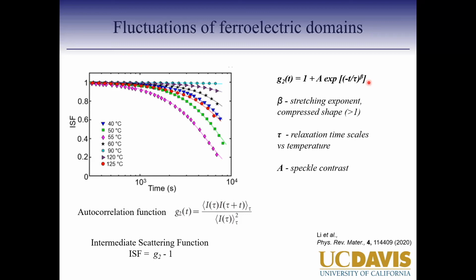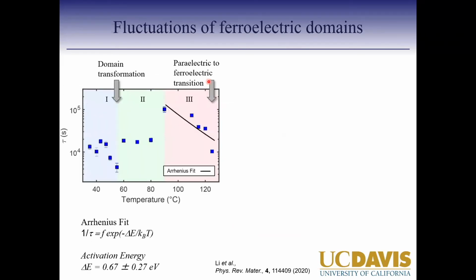Okay, and that's what we saw for all the temperatures, and that's looking to be more of a universal behavior of how ferroelectric domains behave. We have done this for orbital domains and magnetic domains and charge ordering domains, and they all seem to behave in sort of a similar manner. So then looking at the time scales, we can get fluctuation time scales as a function of temperature. And so that's plotted here. We can map out that as a function of temperature.